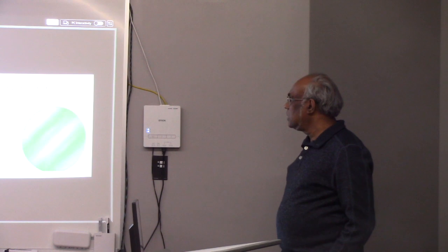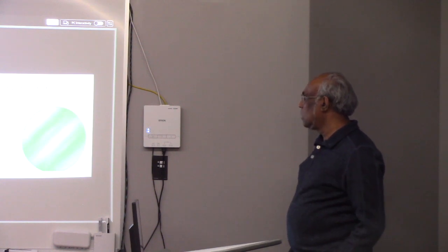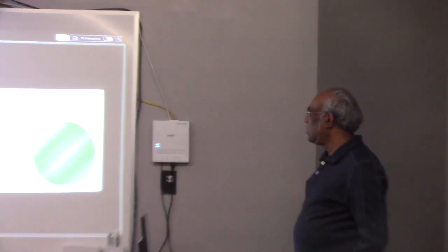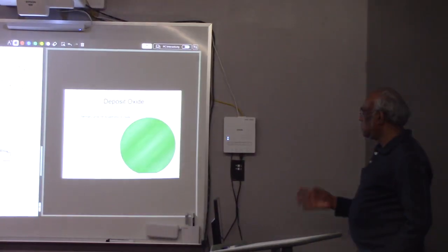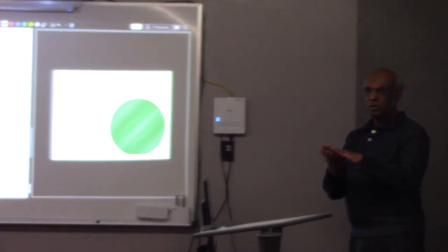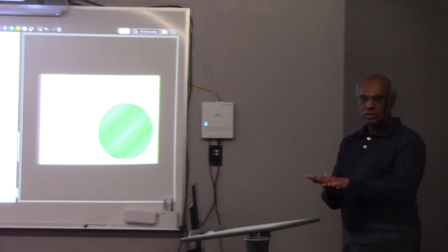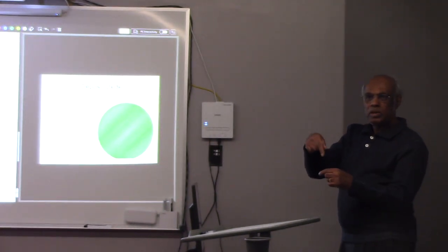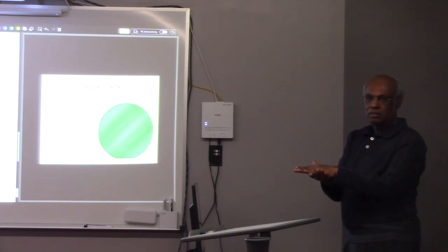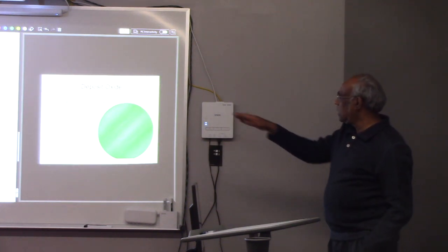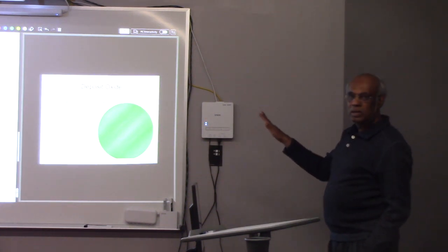Take the silicon substrate, bare silicon. So then what do you have to do? Grow silicon dioxide, right? So that's the second step. Here I put like 5,000 angstrom, that means 500 nanometer oxide. That's standard because if you make it too thin, sometimes you will have something called pinholes. If you want to make an electronic device, that can short, right? So 300, 400, 500, they are pretty good. So now your whole wafer is covered with silicon oxide.